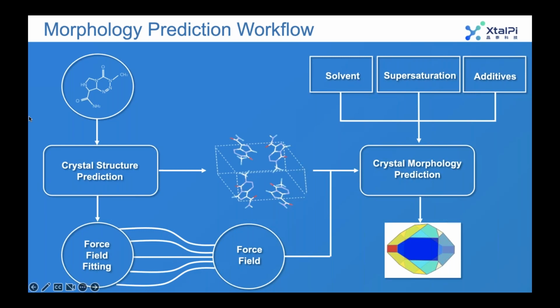So our crystal structure prediction algorithm involves a step for tailor making the force field, because you get these crystal structures and you get different crystal structures specifically, and you can pull out dimers and monomers from those structures and use those quantum mechanical energies to tailor make a force field. So what the truncated crystal structure prediction does is it gives us a data set of crystal structures from which we can draw the dimer and monomer interactions and then tailor make the force field.